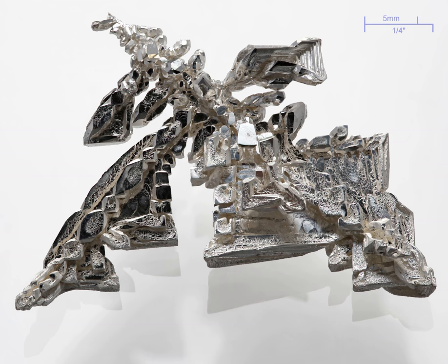Protected silver has greater optical reflectivity than aluminium at all wavelengths longer than approximately 450 nanometers. At wavelengths shorter than 450 nanometers, silver's reflectivity is inferior to that of aluminium and drops to zero near 310 nanometers. Very high electrical and thermal conductivity is common to the elements in group 11, because their single s electron is free and does not interact with the filled d subshell, as such interactions which occur in the preceding transition metals lower electron mobility. The electrical conductivity of silver is the greatest of all metals, greater even than copper, but it is not widely used for this property because of the higher cost.